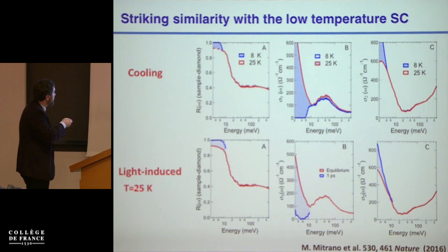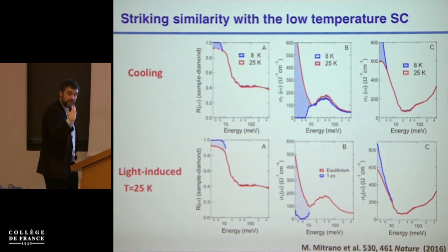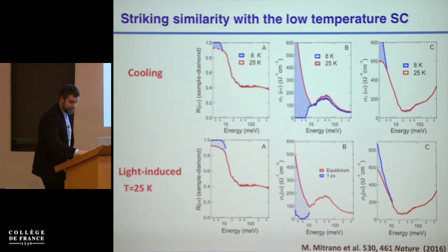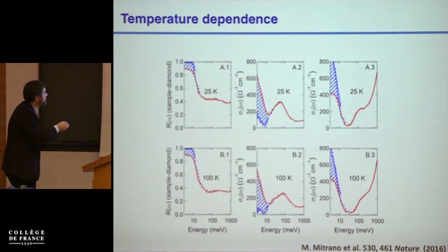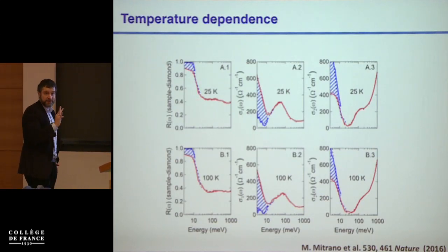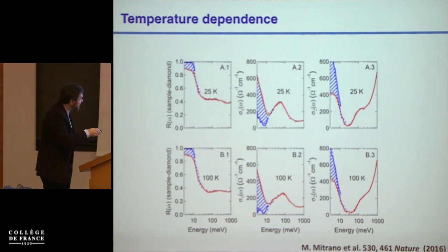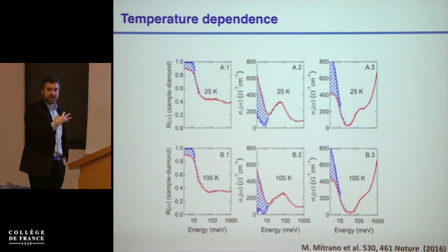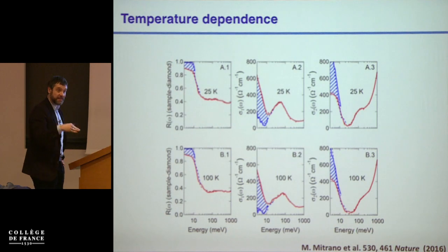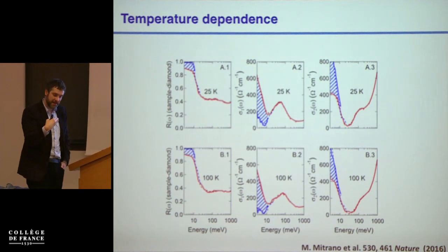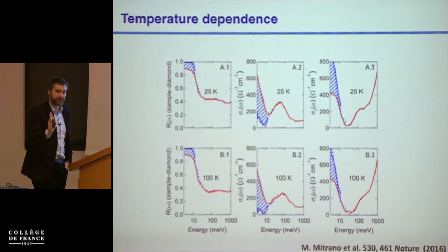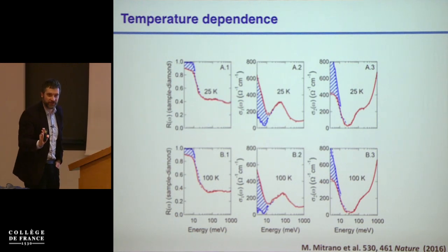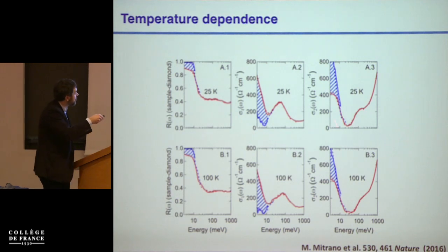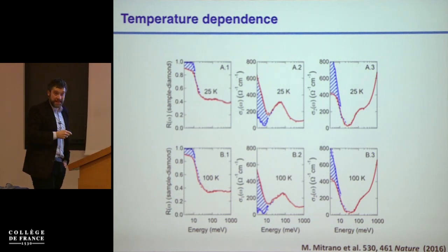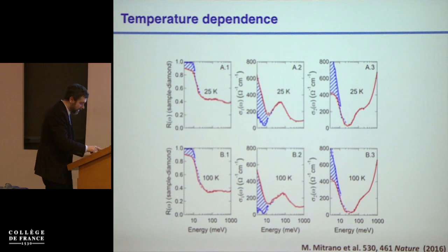And this is observed, in this case, at 25 Kelvin, so 5 Kelvin above equilibrium Tc. And even more strikingly, is observed even at 100 Kelvin, 5 times above Tc. And you can see the gap here in its full glory in something that is really very strongly suggestive of, if this is not a superconducting state, something that has clearly the same optical properties as an equilibrium superconductor. And actually a really remarkable conductivity at low frequencies, okay?